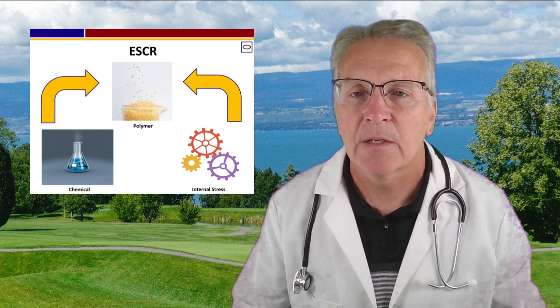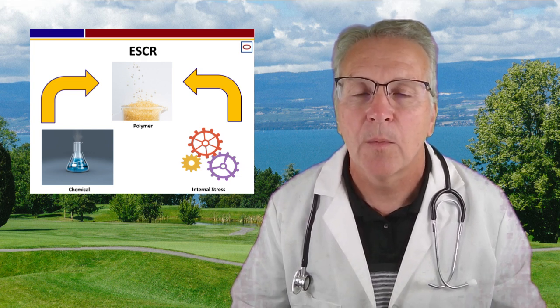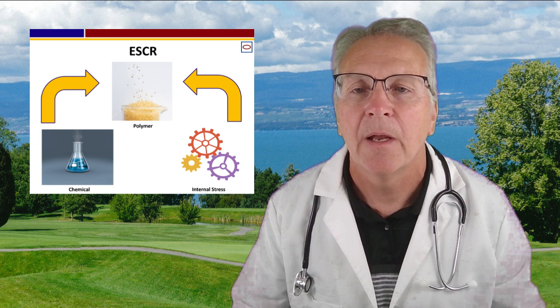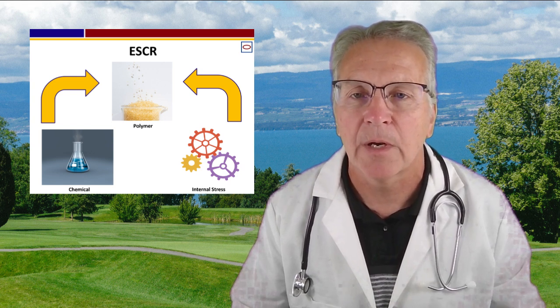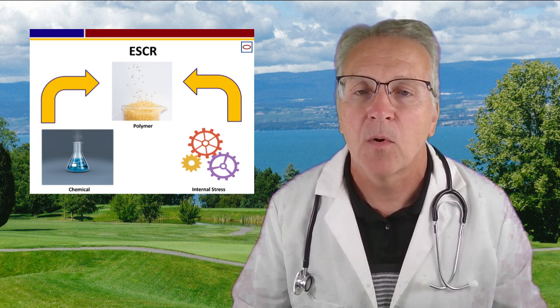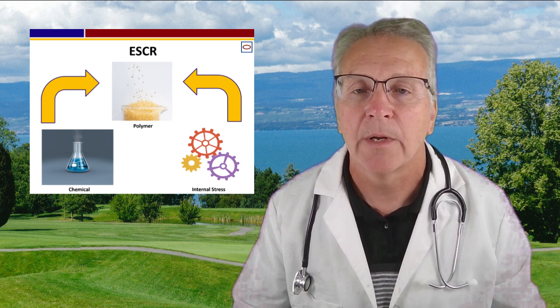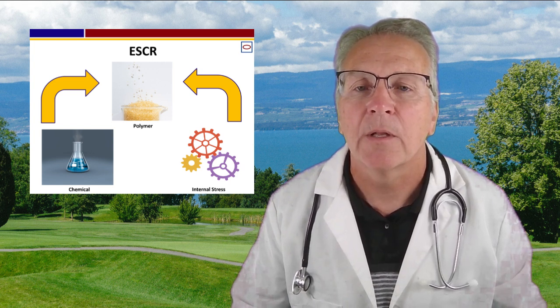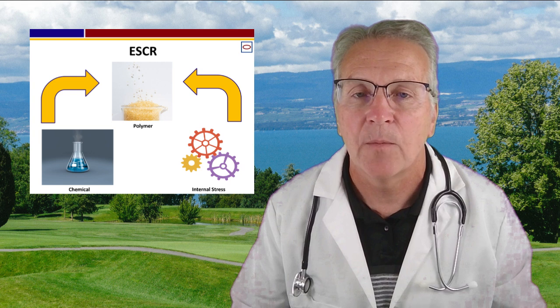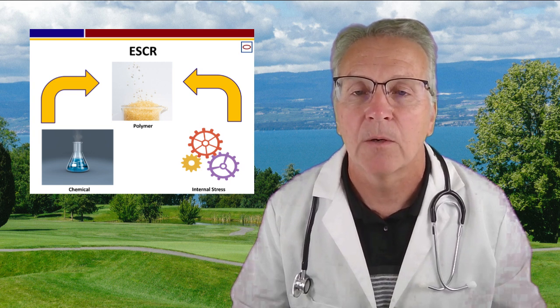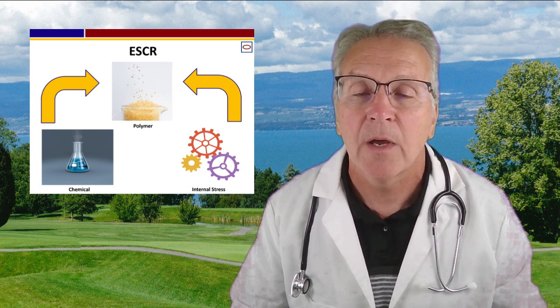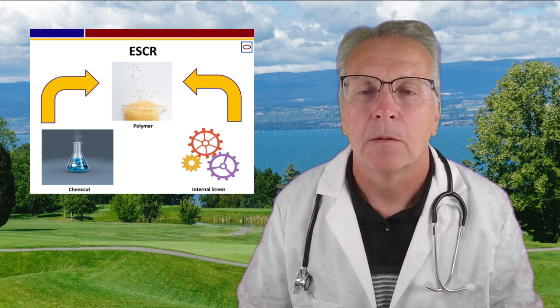And to improve ESCR, you could choose a more robust high-density polyethylene, and or reduce the molded in stress, and or change the chemical portfolio so the parts will not stress crack. And eventually we were able to make the high-density polyethylene survive a water soak and also handle aggressive chemicals.